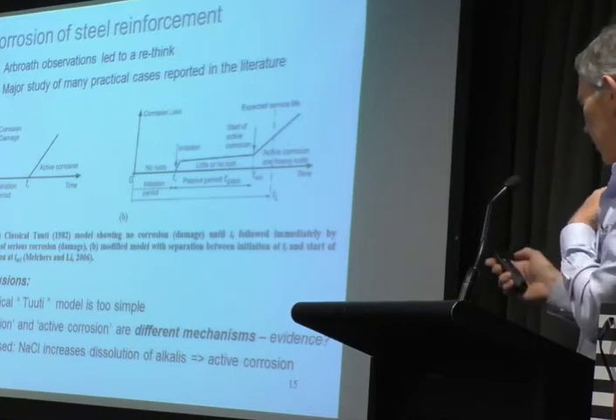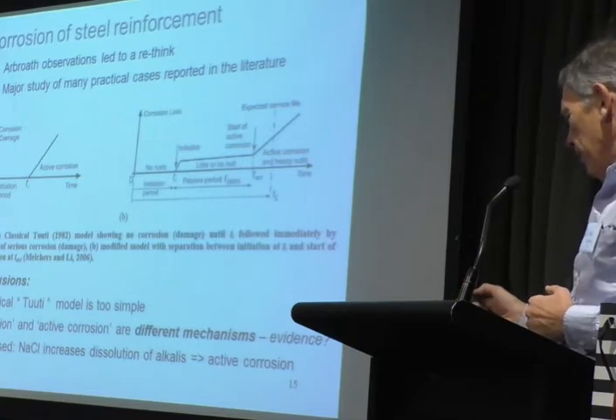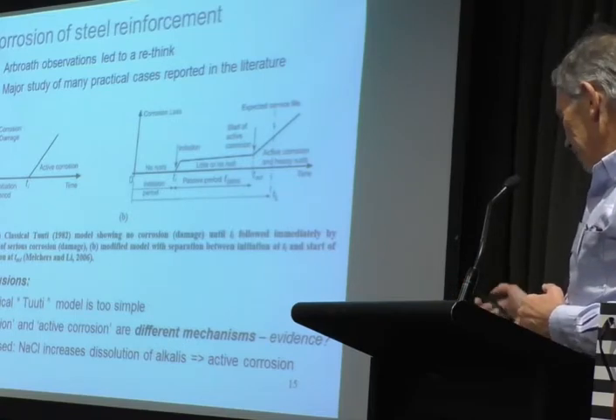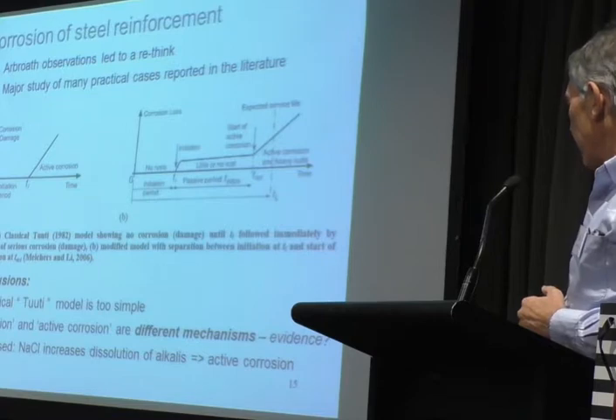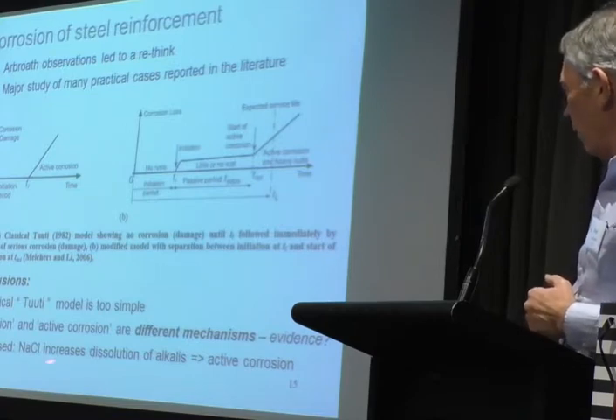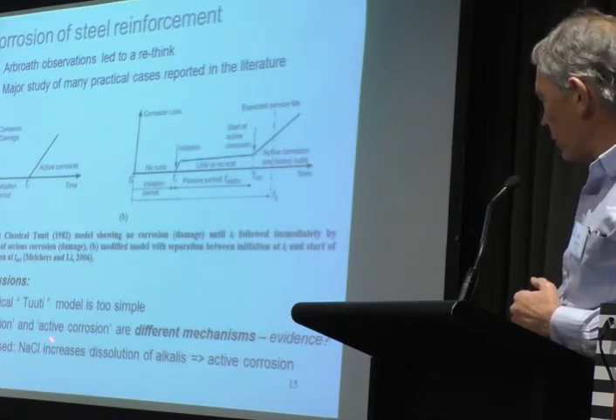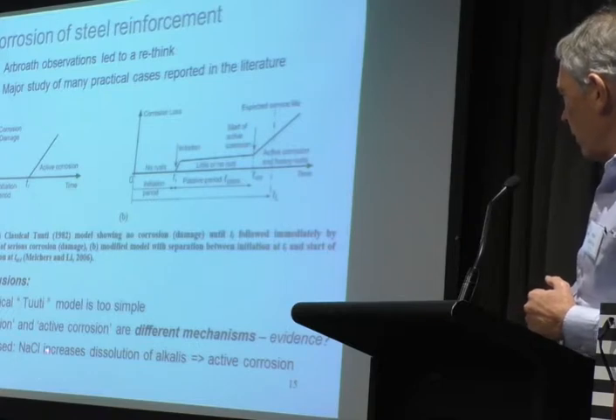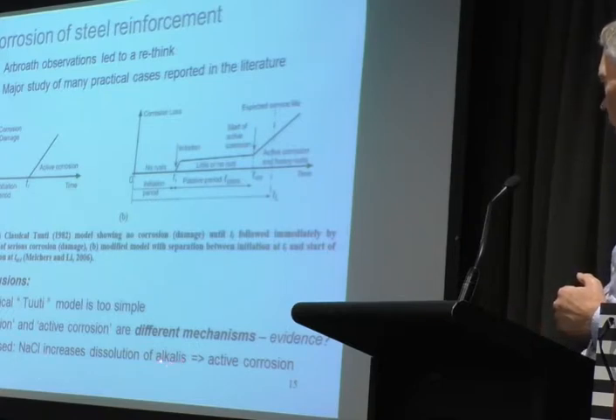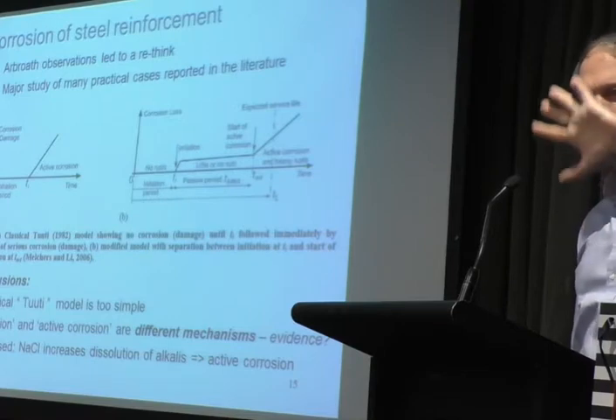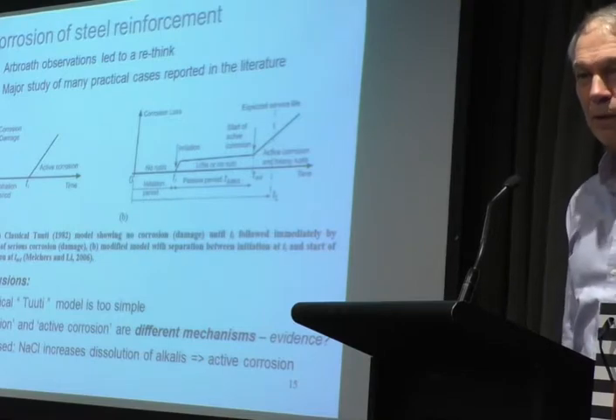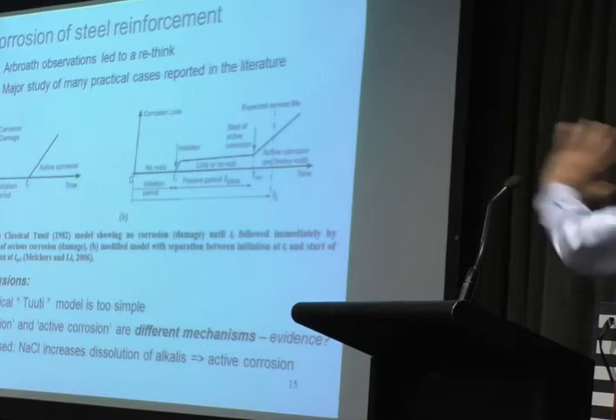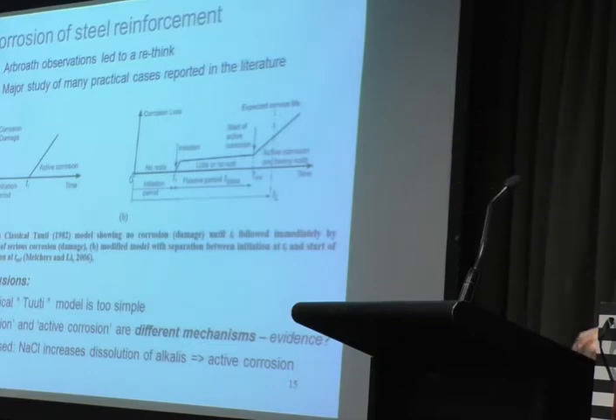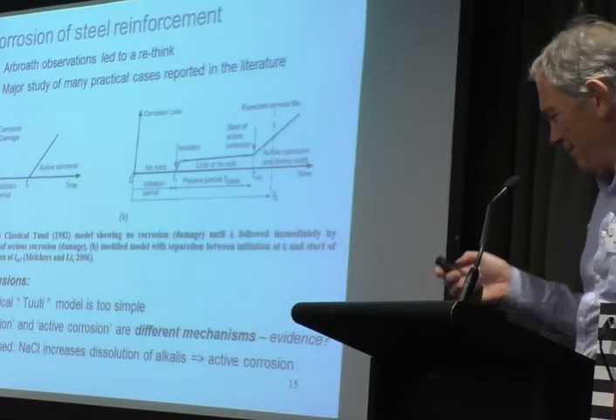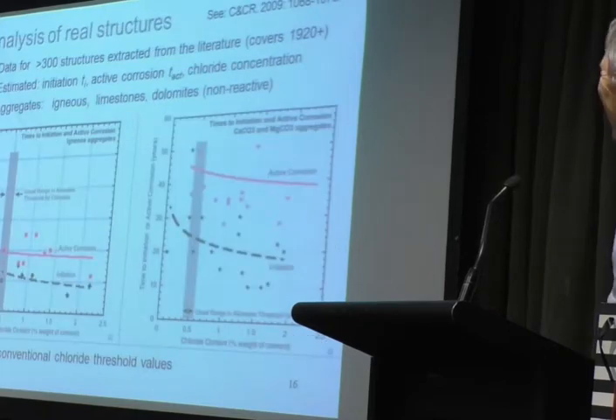And we had this notion that the most likely thing is that somehow the chlorides, in particular sodium chloride, increase dissolution of the alkalis in the concrete. Now, there was a little bit in the corrosion literature to tell us that this was a possibility, but we had no evidence. So we just put it out there and said, this is what we think is happening. And the paper got published anyway, so it must have been all right.